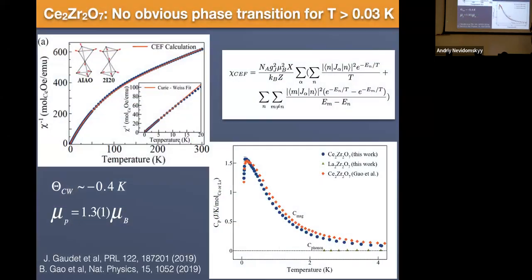Okay. So these were some of our very early measurements on cerium zirconate. Very similar measurements were done by Pen Chang here. I'm showing you inverse susceptibility versus temperature on this plot, and our heat capacity measurements along with Pen Chang's heat capacity measurements on an independent crystal that's shown over here. The main thing I want you to take away from this data is just that there are no sharp features in it. Okay? A phase transition to some sort of ordered state or some sort of frozen state would appear as a sharp feature in this sort of data and other data.